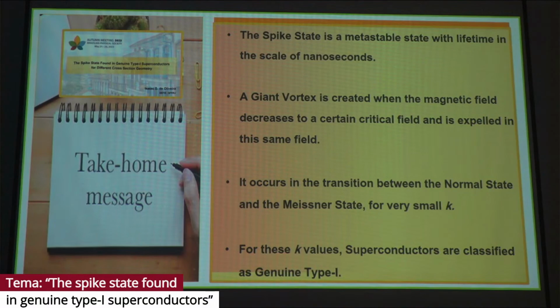Take-home message is that the spike state is a metastable state with a lifetime on the scale of nanoseconds, and a giant vortex is created when the magnetic field decreases to a certain critical field, and it is expelled in the same fields. It occurs in the transition between the normal state and the Meissner state for very small values of the Ginzburg-Landau constant. For these kappa values, superconductors are classified as genuine type 1 superconductors.